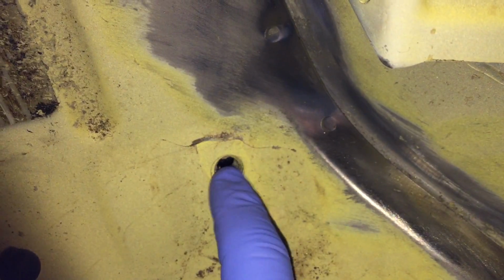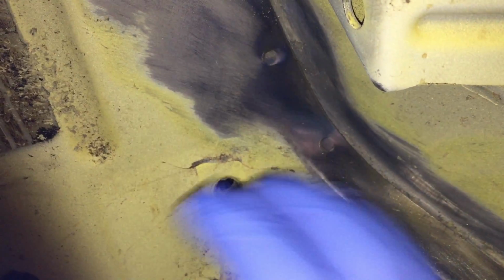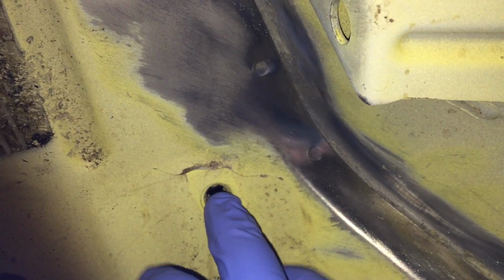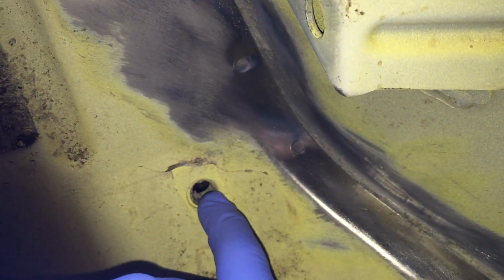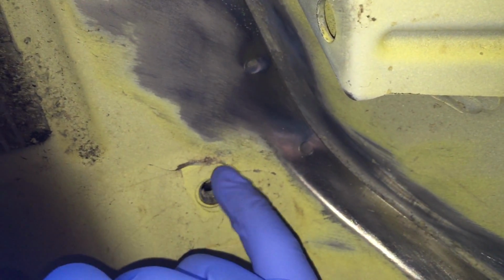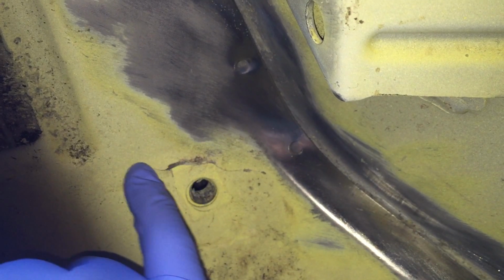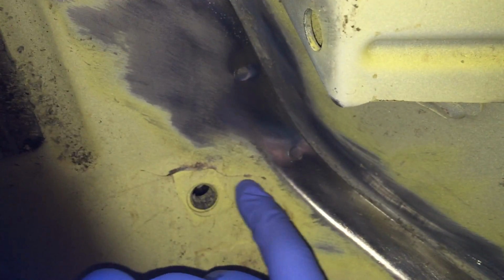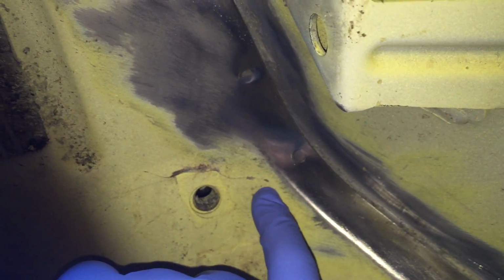And going over to the other side, this is a bit rarer, but I've seen it a few times. This is the Isofix mounting hole, one of them, and this is where you would put your child seat, one of the two holes on the passenger side, and there's a crack going all the way across the top of it. So it starts somewhere around this point here, because bear in mind that thread is in the rear axle carrier panel, the one that's obviously getting all the loading from the subframe itself. So the crack is starting from the middle, we think, and then heading out, it finishes about there, and then going over towards the edge of the panel and finishes here at the moment.